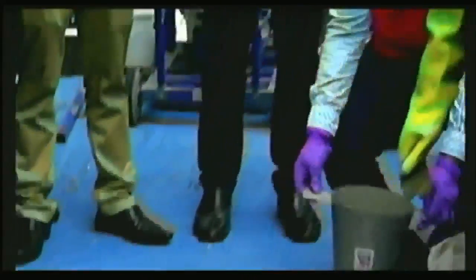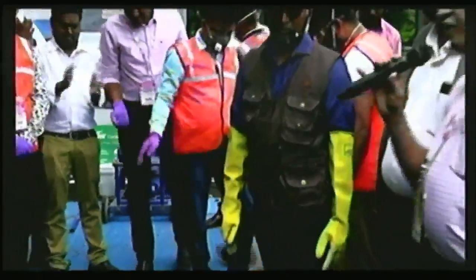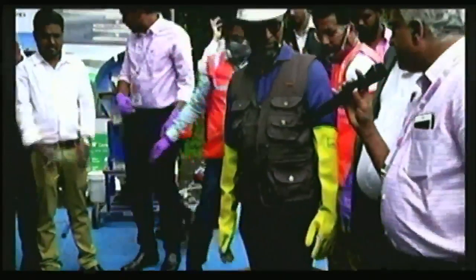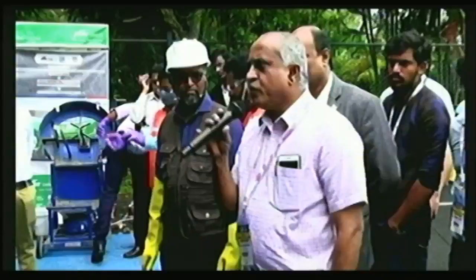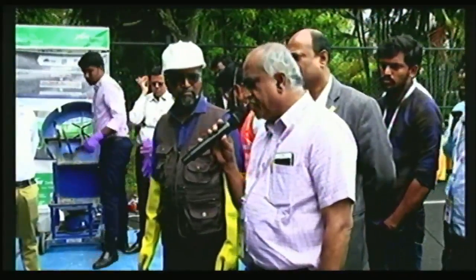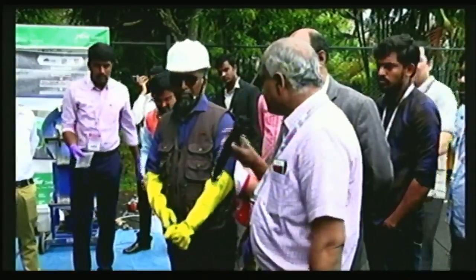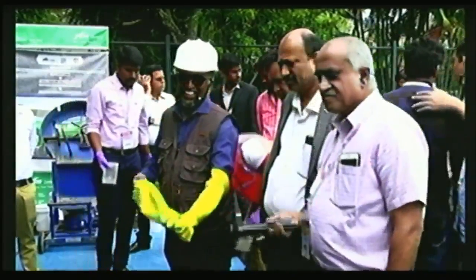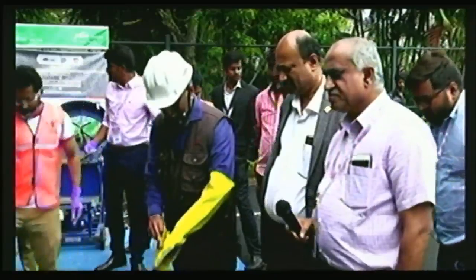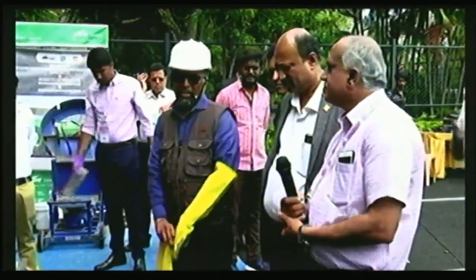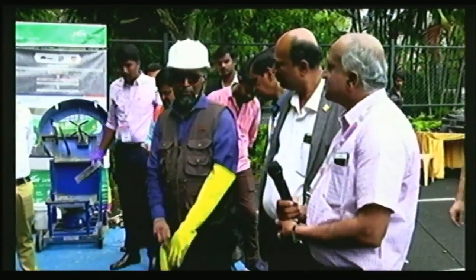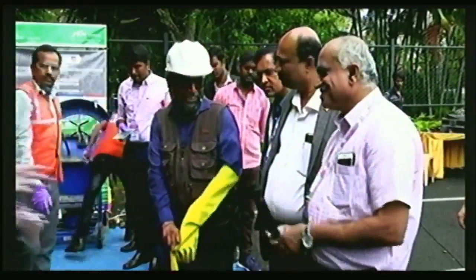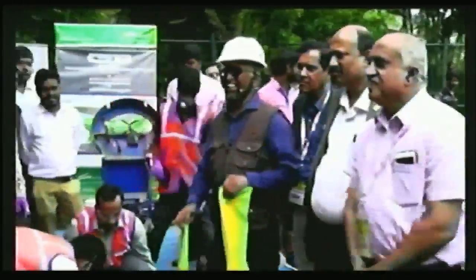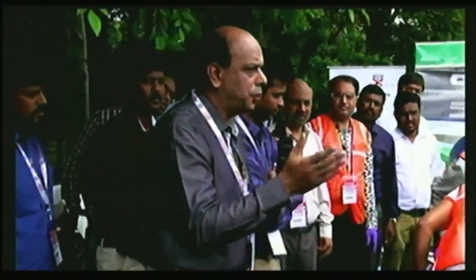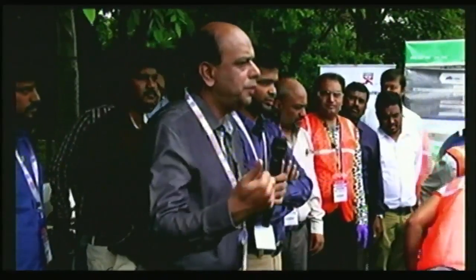I have a question. With 70% replacement of GGBS, what would be the 3-day strength and 7-day strength of this particular concrete? Yeah, we have just shown this in the presentation. Me and Rajendra both have access to it. So at 3 days, normally what we are getting is between 16 to 19 Newton per millimeter square. When you go with the 50-50, you get about 18 to 20. There's a small difference between these. But when you go to 7 days, we are getting M30.